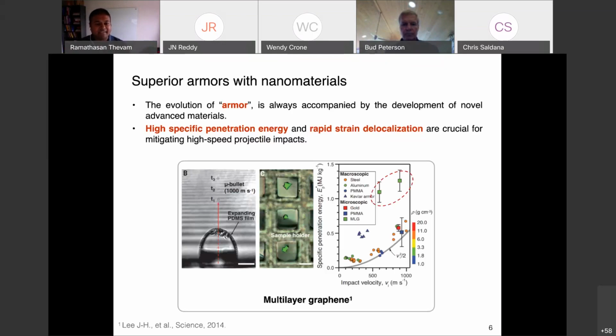In the nanomaterials regime, one of the very first studies done with this microballistic system was on graphenes. Multi-layer graphene was shot by microprojectiles. It has been shown that graphene has superior specific penetration energy compared to other bulk protective materials such as Kevlar, PMMA, aluminum, steel, and also some other nanomaterials. This was the first promising result that launched us towards the nanomaterial regime. And of course, we have now developed much better materials that I will show you shortly.